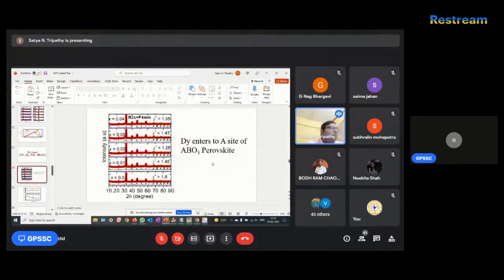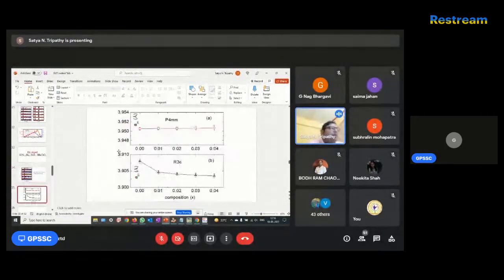Okay. So if we dope that, here we observe that Dy enters into the A site of the perovskite structure. How did we understand that? We can see that from lattice calculation: the lattice parameters in the P4MM phase remain constant, whereas the R3C phase decreases. So this basically allows us to say that dysprosium is not going to the B site, that it is going to the sodium or bismuth site, because the R3C phase is decreasing. So this kind of information we got from this, about where the atom stays.